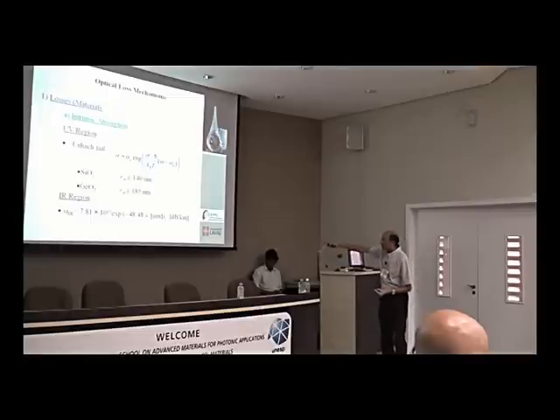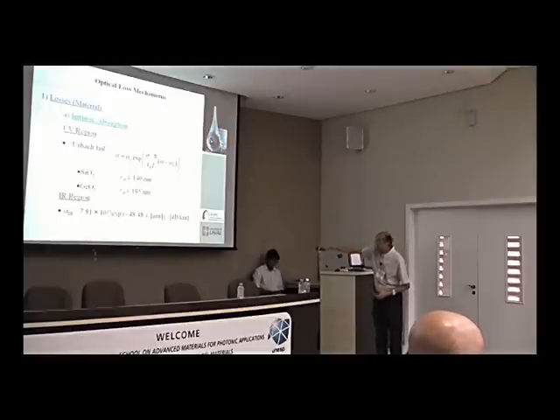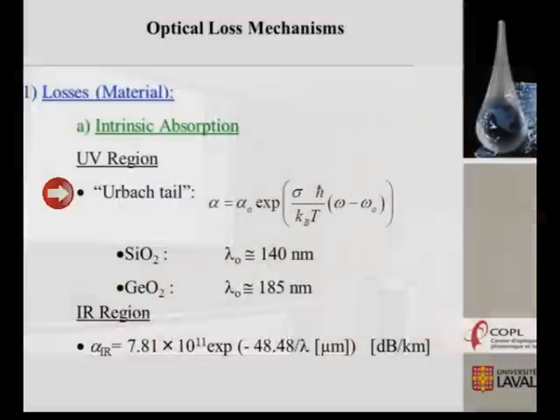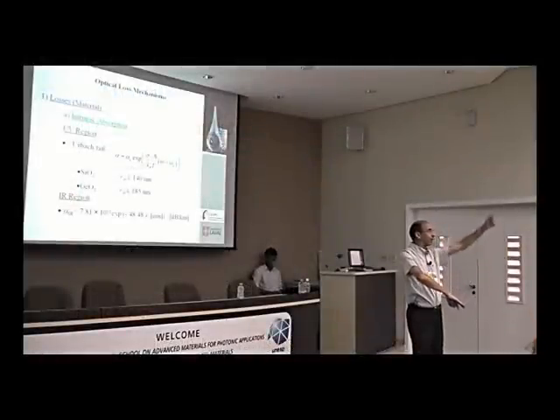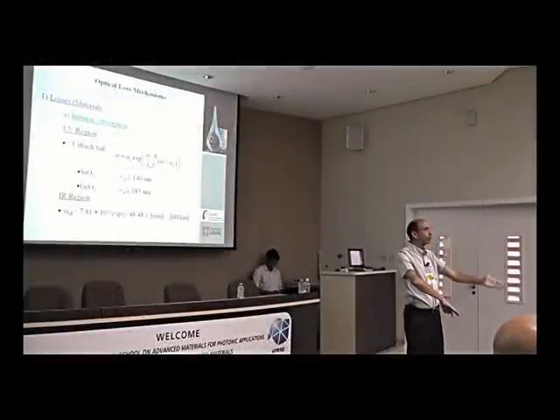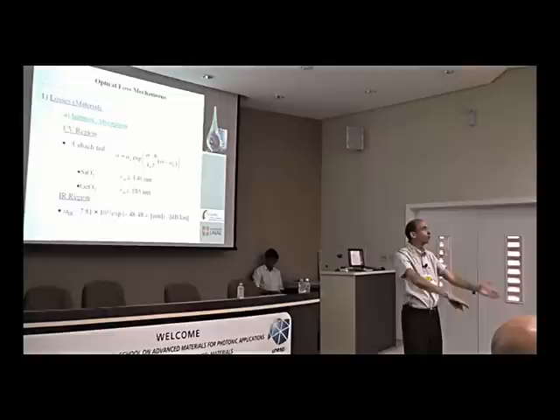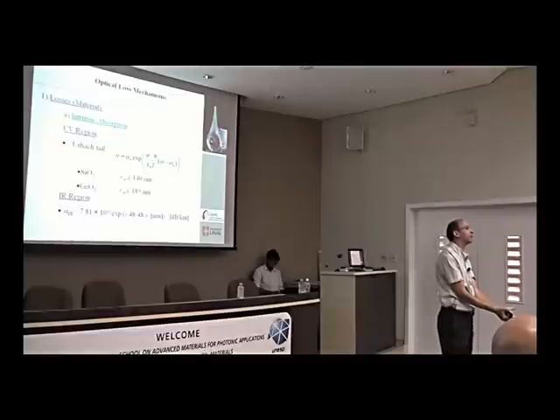In silica glass, it is this equation, a constant times exponential of minus another constant over lambda. This is something very important, that when you see it in the curve, it will be something like that. Remember, in the UV we are coming with this curve, and in the infrared we are coming with this curve. If we put the two together, we have a V. This is what we call the V curve.